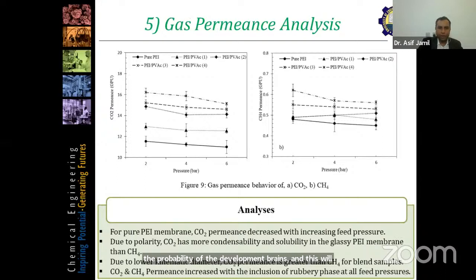And if we look at CO2 permeance, in the first graph, the pure polyetherimide is shown as a bold black line. We ran our membranes at 3 pressures: 2 bar, 4 bar, and 6 bar, and on the y-axis we have CO2 permeance. So we see CO2 permeance is decreasing with increasing pressure, which is again expected because the pores are filled with CO2 molecules, and when you increase the pressure, the permeability goes down.